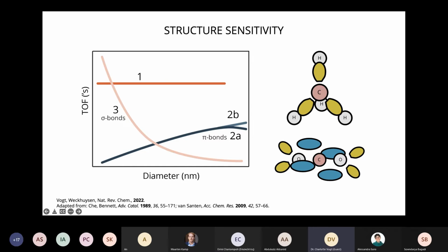And the type of structure sensitivity that you see is that the smaller a nanoparticle goes, the less of the types of sites are available to cleave those pi bonds, and thus you see less activity. And that's actually the way that we define structure sensitivity. Does the turnover frequency, the surface normalized activity, change with catalyst particle size? So pi bond structure sensitivity we have observed. We also know that there is sigma bond structure sensitivity, for example, in steam methane reforming, where the cleavage of a sigma bond of the CH bond of methane is the rate determining step, generally speaking. And there we actually see that those bonds are preferentially cleaved for smaller nanoparticle sizes, preferentially over a highly under-coordinated site. So the smaller you go, the better the activity becomes, the surface normalized activity becomes.